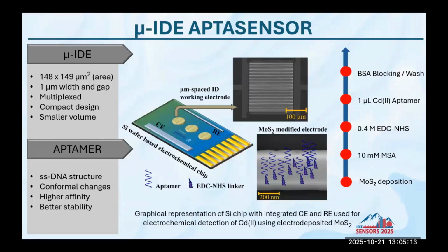In order to fabricate these kind of sensors, the steps we have taken is we try to electrodeposit the material on top of these working electrodes, which will help us to remove the leaching step, which was a major concern in case of glassy carbon electrodes. Next, we are trying to modify the material with the aptamer by using the EDC NHS and surface functionalization chemistry. The amine-terminated aptamer is cross-linked through EDC NHS cross-linker to the material to prepare the sensor.